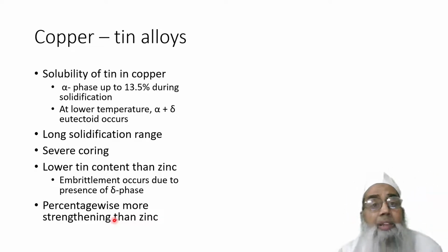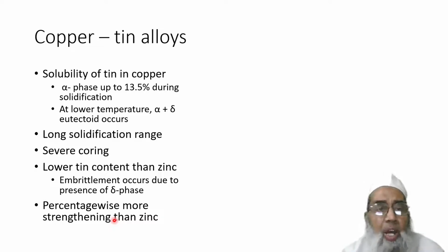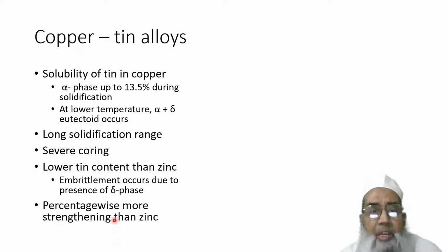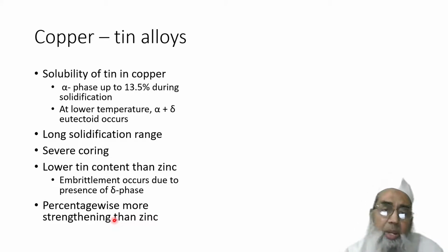Another important alloy is the copper-tin alloy, in which the solubility of tin in copper is in the form of alpha phase. It is up to 13.5% during solidification. At lower temperature, an alpha plus delta eutectoid occurs. Here also, similar to zinc, there is a long solidification range, and hence coring and segregation of dendrites take place. This segregation of dendrites causes embrittlement and also restricts the feeding mechanism, and this is all due to the delta phase.